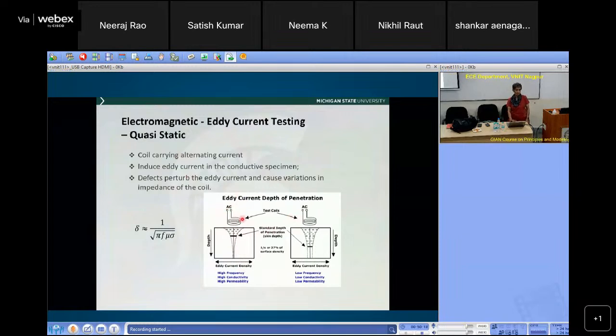So the same coil, if you just scan the surface with this coil, the impedance of the coil will change based on the underlying condition. Okay. And we'll talk about it more deeply. So a simple coil is a nice sensor. There's no contact involved. You can keep it a couple of millimeters away, and then get information about the defects. Of course, because of what we call the skin depth, it is sensitive to the surface. At most, it can go up to half an inch depth. So it's ideal for aircraft. Aircraft has each aluminum layer about half an inch. So if you have 1, 2, or 3 layers, it can even pick up defects in the second layer.